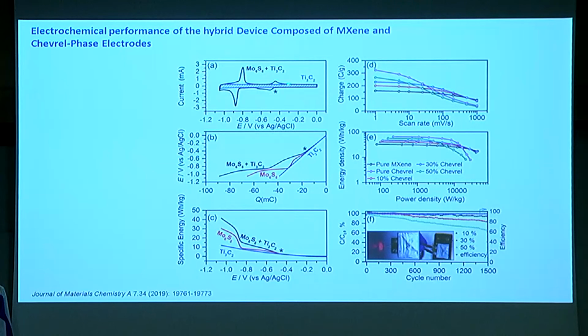You can see here the CV is simply a combination between the capacitive-type response and the contribution of the Chevrel redox. And basically, by playing with the concentration or the mass fraction of the Chevrel in the MXene, we can get an optimum value of both energy density and power density. I will not get into much detail, but this is an interesting calculation of how you can calculate exactly the contribution of each fraction. But anyway, we get very good cyclability for this system. So this is the first alternative for the lithium TFSI.